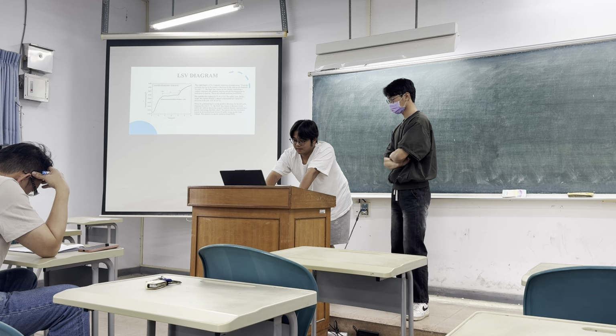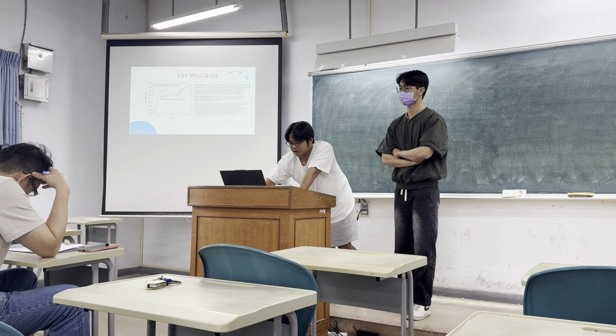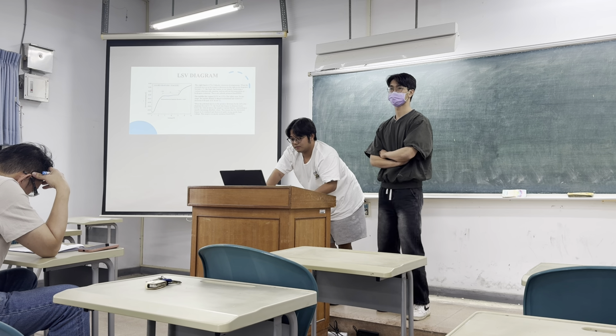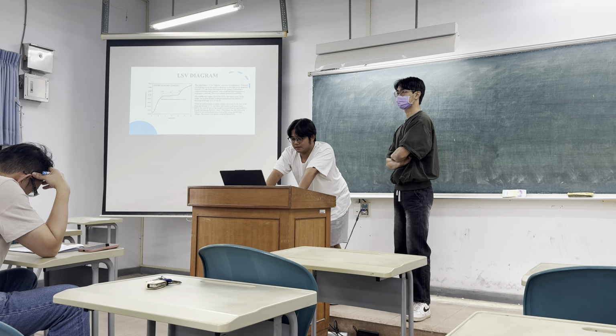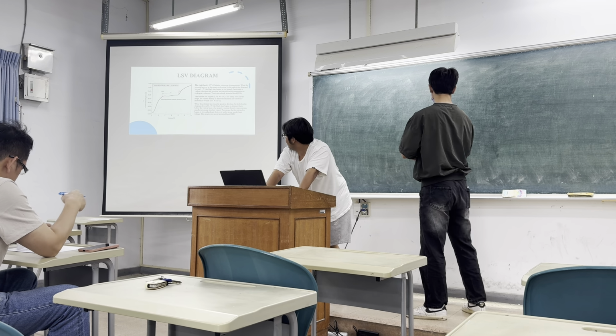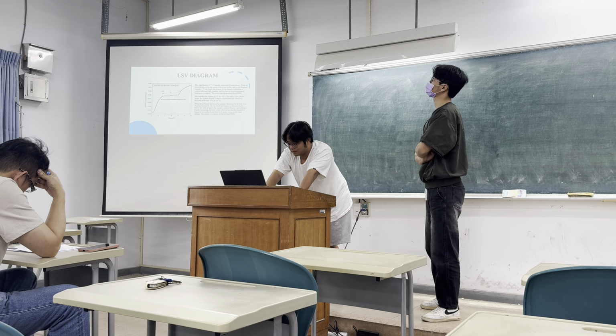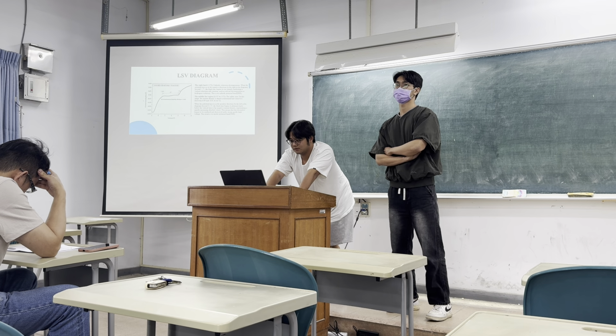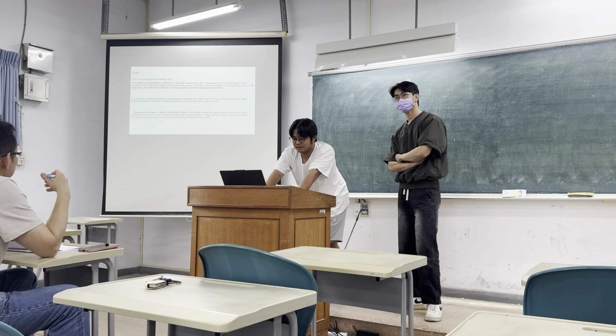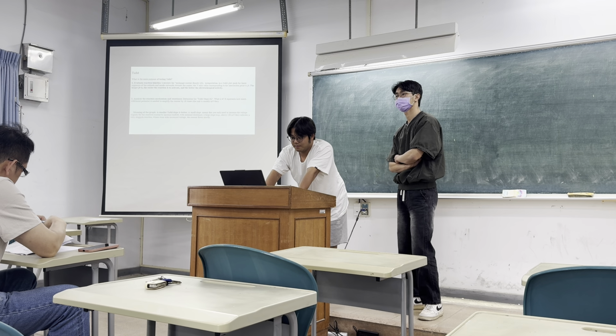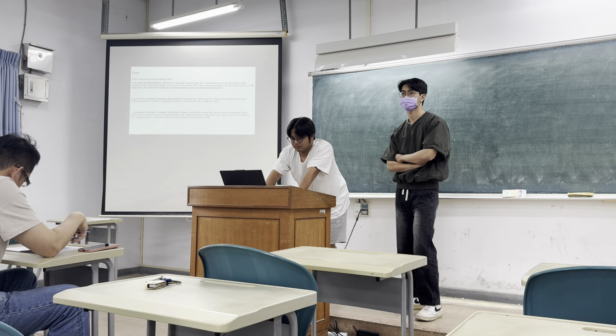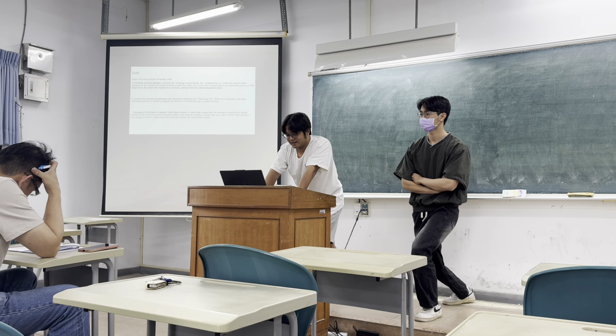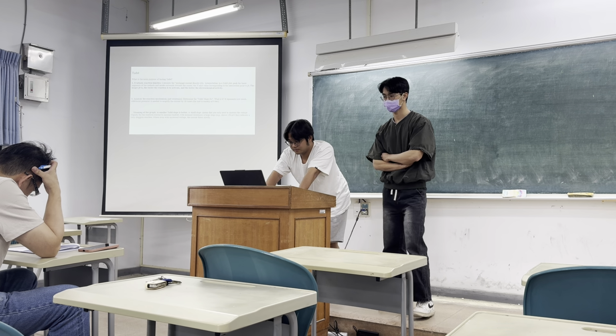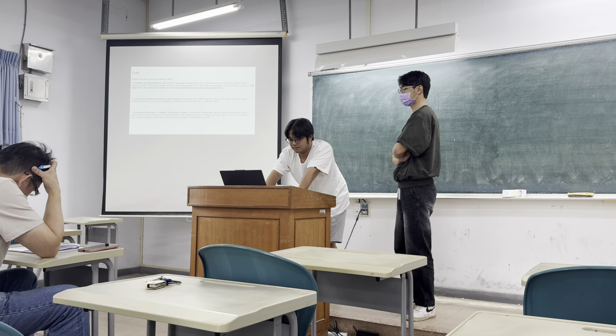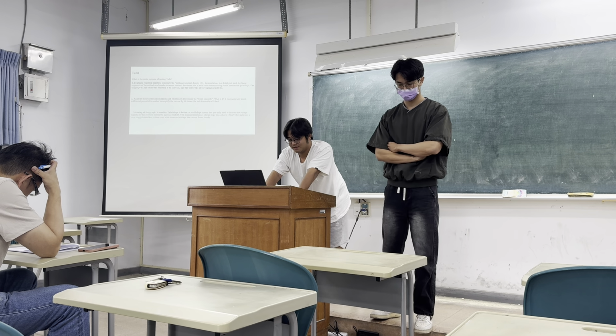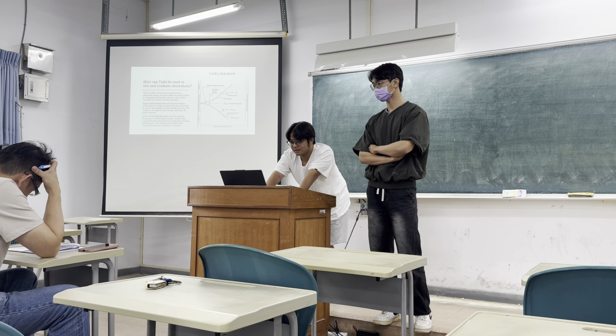We can see that in the middle there are 1.5 volts and -1 volt, and from this area we can calculate the ESW, and the larger the ESW, the more stable during charging and discharging. And the next one is Tafel. The main purposes of testing Tafel: one is to evaluate reaction kinetics, calculate the exchange current density. And the next one is to analyze the reaction mechanism and resistance. And this is